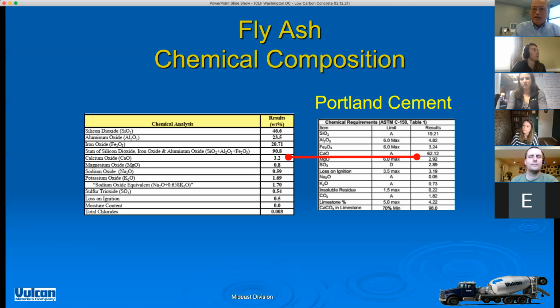We have ACI certification classes and stuff like that, and the technicians have to run through various test methods in concrete and so forth. One of the things we use as fake concrete is simply fly ash. After they're done, they can dump that sample back into the pile, and that pile's been there for 10 years, and we keep using it and keep using it. So that shows how unreactive fly ash is. Relatively speaking, slag cement, if you add water to it, is actually going to get hard. Slag and water, it's hydrating. It can get hard, and it can get some significant strength. So, next slide, please.